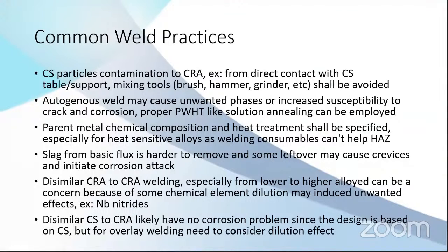But for carbon steel to corrosion resistant material, normally there is no problem, because the design is normally based on the carbon steel. But if it's overlay welding, please consider the dilution effect, because the corrosion resistant material can have a reduction in chemical elements, so it has less resistance than before.